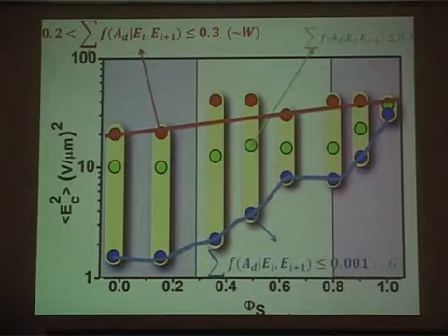The system, there's a small crack up here, and I get the light coming in, so I measure this thing. But if I want to flip this out, a large thing totally up, then I have to overcome the deepest potential minima that this flake is in. And since both of these films are on ITO, I don't expect the adhesion potentials to be dramatically different. The adhesion potential is similar. So this parameter, the red line, red spots, are a measure of what I would say is my adhesion potential.